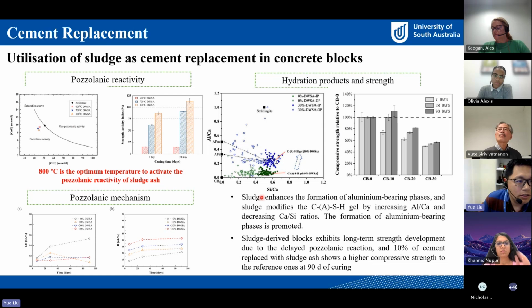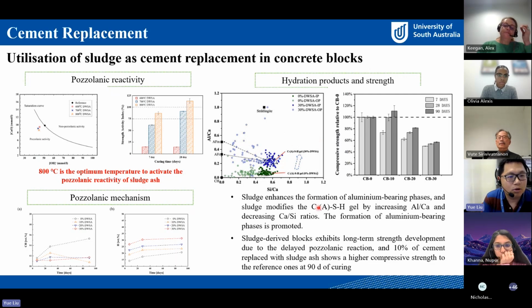Based on the chemical element mapping for the sludge and cement binder matrix, we found the sludge modifies the C-S-H gel by increasing the aluminum to calcium ratio and decreasing the calcium to silica ratio. Also, we found the formation of aluminum-bearing phases is promoted.